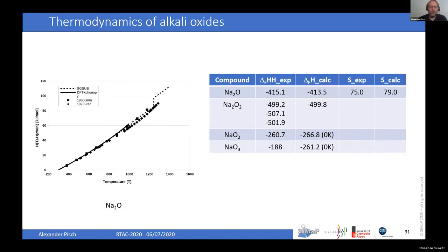When it comes to sodium oxide, there are only two heat content measurements, and that's all. So again, the heat of formation we calculate is in very, very good agreement with the literature values, the measured values.